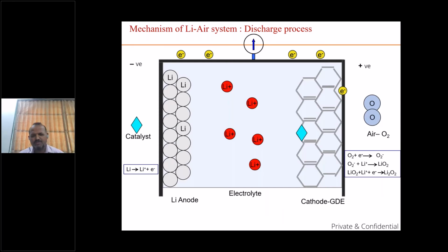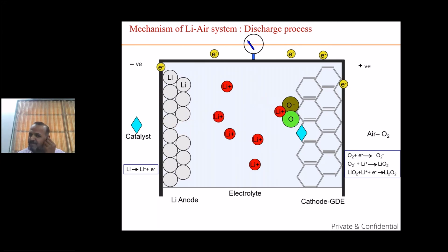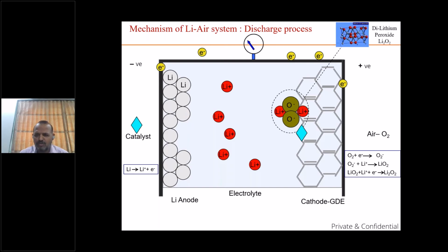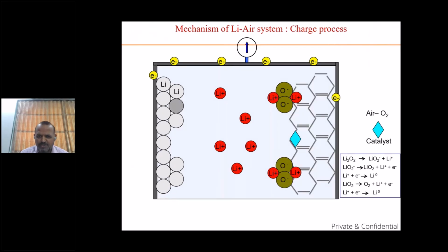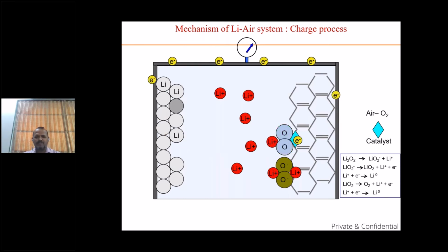So to give you an example, I just wanted to show you, there is a lithium anode, then electrolyte and gas diffusion electrode. So during the discharge process, oxygen is coming from the air and can react, then the electron transport happens. Then you can see the lithium ions react with the oxygen, react with the catalyst, and you can form Li2O2, lithium peroxide. And during the charge process, this lithium peroxide can react with the catalyst and have the transport phenomenon from anode to cathode. You can see oxygen can come out.